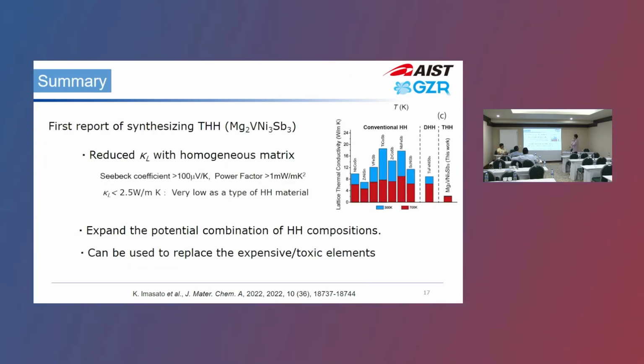So this is the summary. I think this is the first report of synthesizing triple Half-Heuslers, even though this is completely disordered. I think the reduced lattice thermal conductivity is interesting to investigate further. And we have a decent Seebeck coefficient and power factor. I think this result can expand the potential combinations of elements to design Half-Heusler compositions.